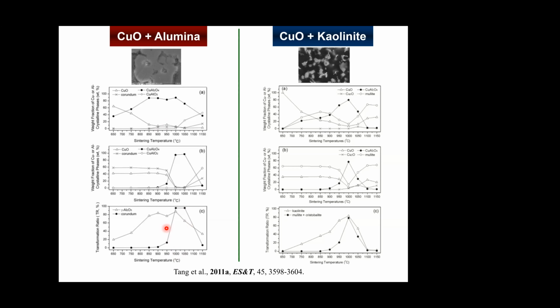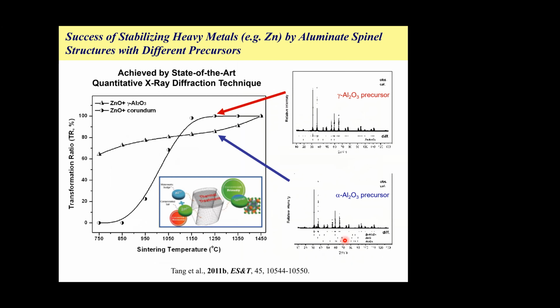You cannot be too low in terms of temperature because you don't have enough incorporation capability. You also cannot be too high in temperature because you make it transform to another phase. So this is an important lesson for us to understand. We have to control things at the right range, otherwise we will not get the best result. A similar situation also happened in the kaolinite system. We also found, very similarly, around 1,000 degrees Celsius for incorporating copper. That's the best temperature. You should really pay attention and take advantage of that window.